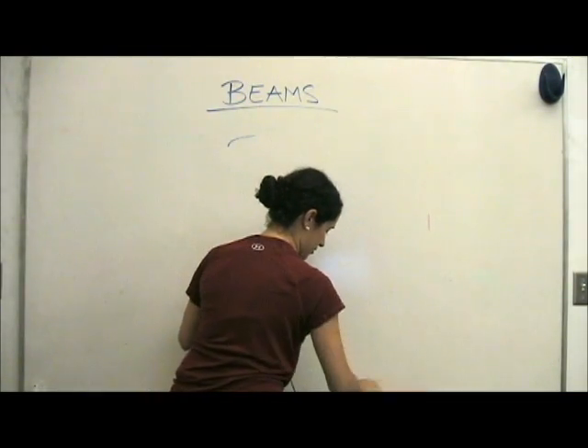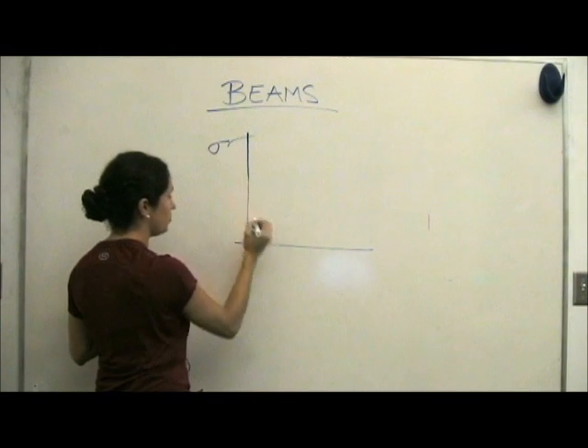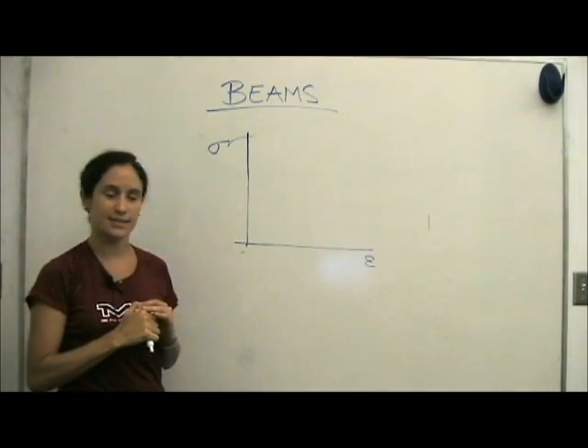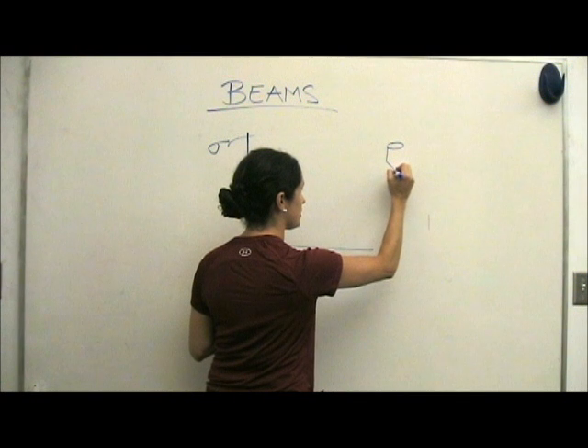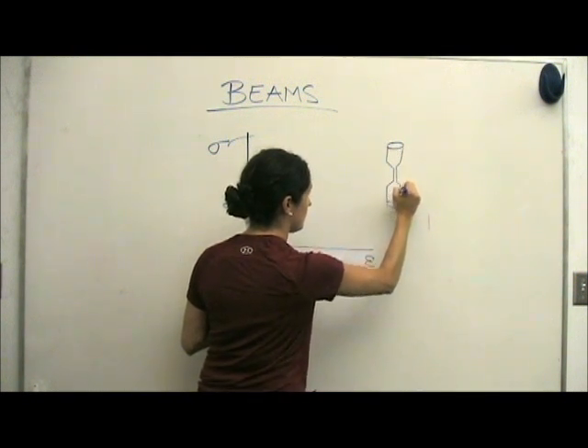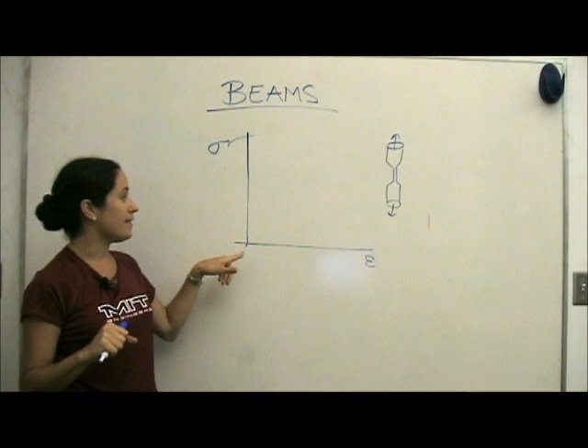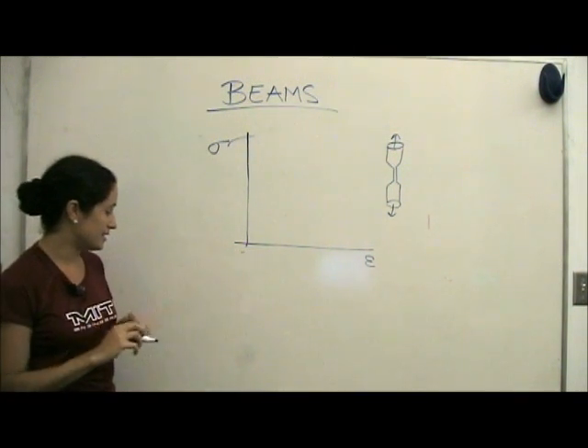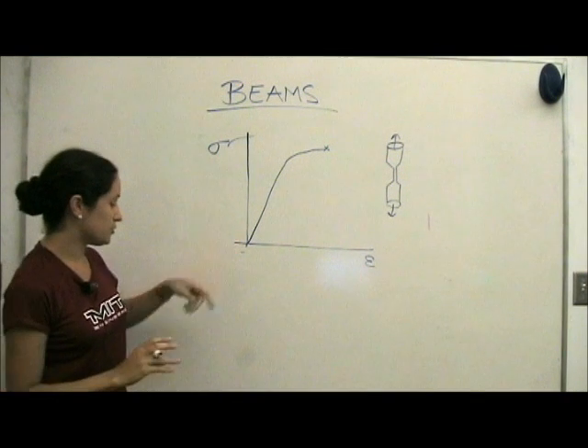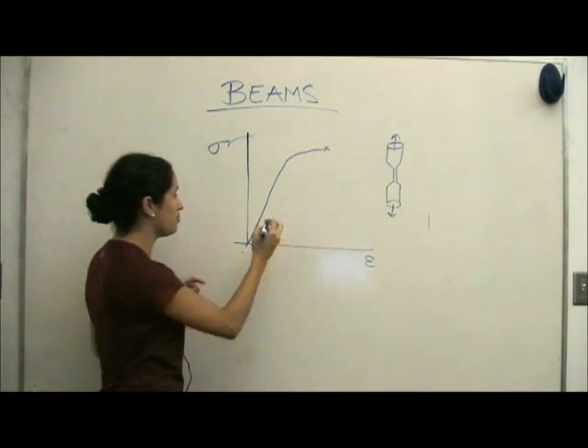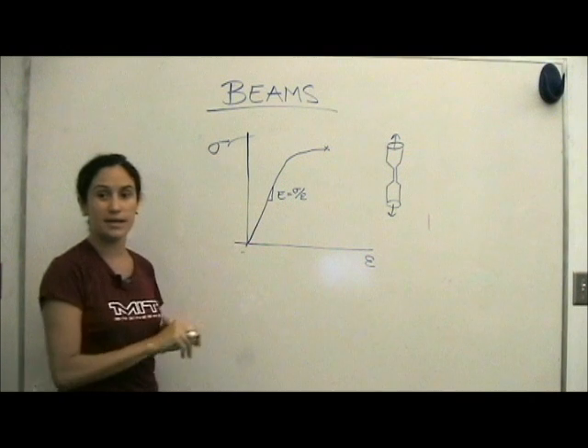The best way to understand the Young's Modulus is to look at a graph of the stress versus strain. So we're going to have a graph here where we're going to have stress on the y-axis and strain on the x-axis. The way these graphs are collected are actually in machines that test samples. The samples usually look something like this where there's a necking section. And what the machine does, it pulls on the sample, it measures the stress that it needs to pull on the sample with, and then records how much the sample deforms under the load. What we end up getting is something that looks kind of like this. There's a straight portion, then there's a bend, and usually there's a limit. The straight portion here, if we look at it, is a slope, which is the stress versus strain, which we already said is the Young's Modulus of the material.